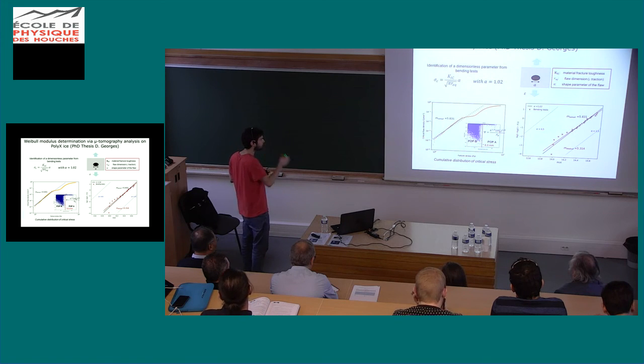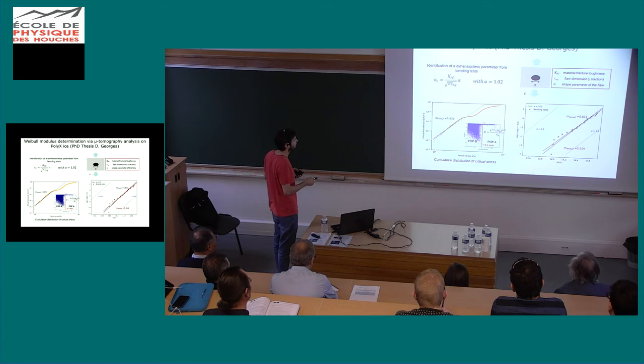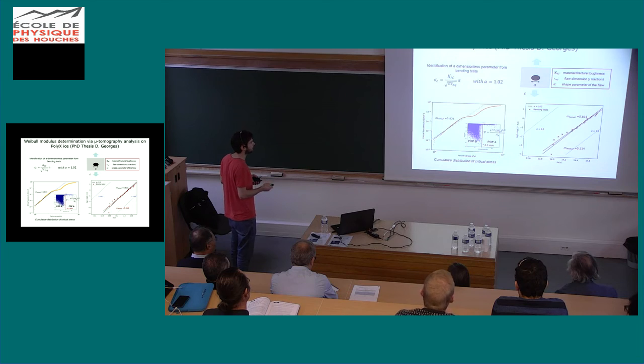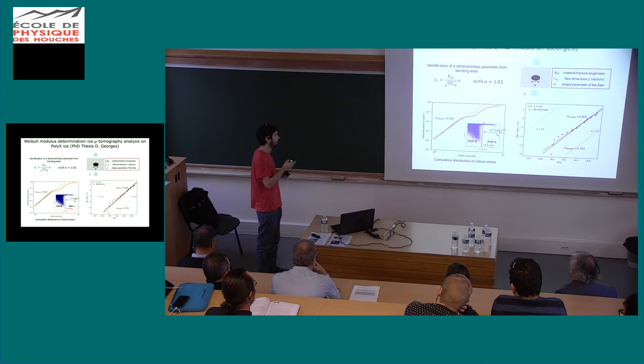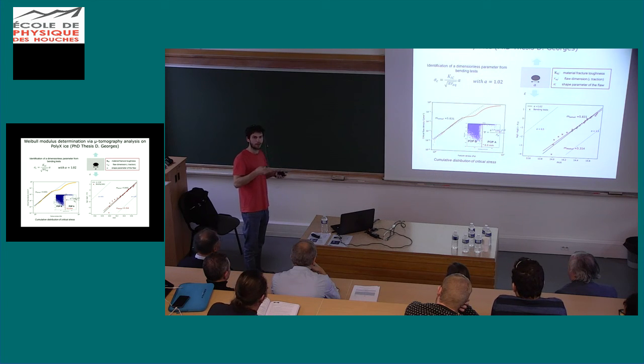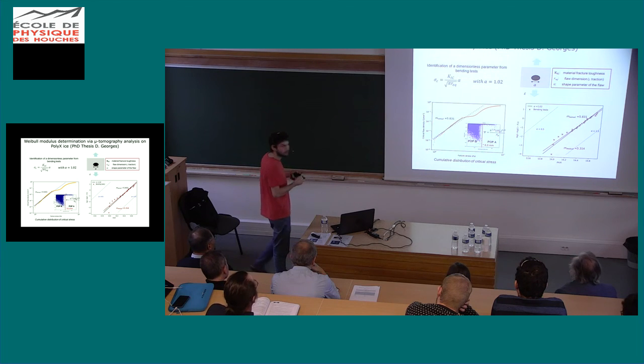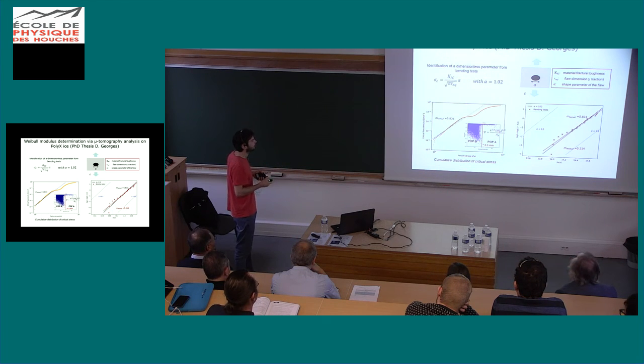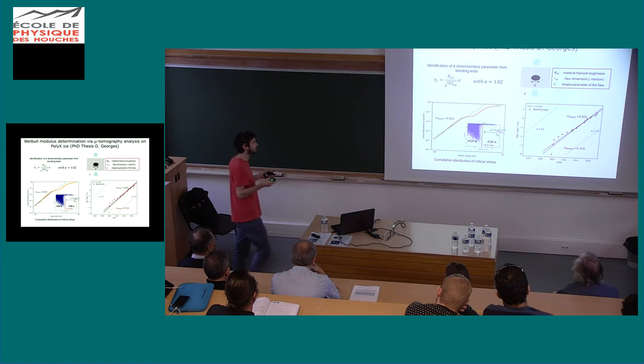And if we focus on the first part of this curve, we can see that the largest porosity seems to follow a power law. So it's possible to plot a pseudo Weibull modulus on these large porosities. The value is about 5.8 for the Weibull modulus, very close to the value found during the bending test. So it means that during this test, we actually solicited the largest porosities only. And that's why the shape parameter is very close to 1, because we are dealing with spherical porosities.